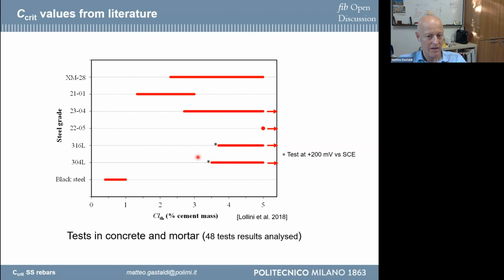For the traditional stainless steels, that is 304L, 316, 2204 or 2205, you can observe a generally very high corrosion resistance, with a chloride threshold that is also higher than 5%. That is an amount of chloride that is not so easy to find in real structures. And for 304L and 316L, there is only one research study that shows a corrosion initiation at around 3.5% of chloride, related to tests of Professor Sorensen, if I remember well. It is a test in which you have a polarization of the rebar, and plain rebar was used, not a ribbed bar. So there is some difference.